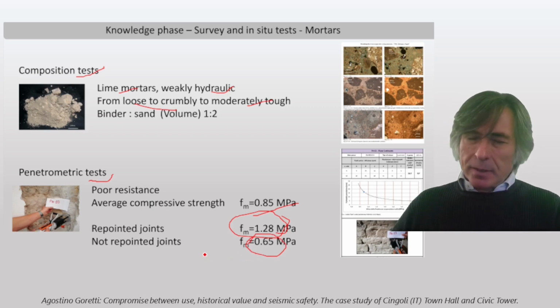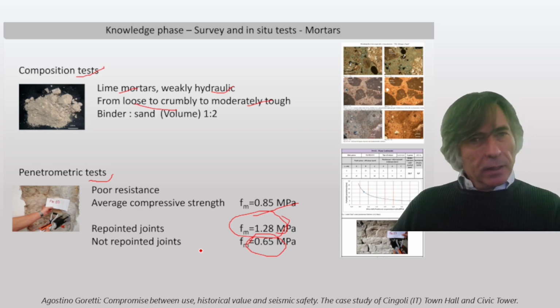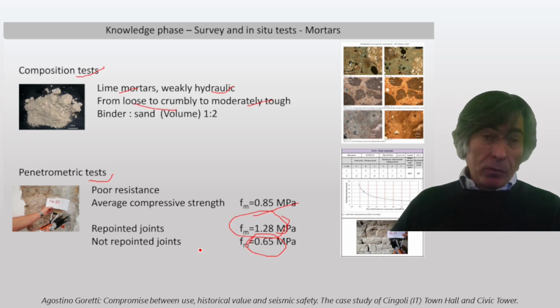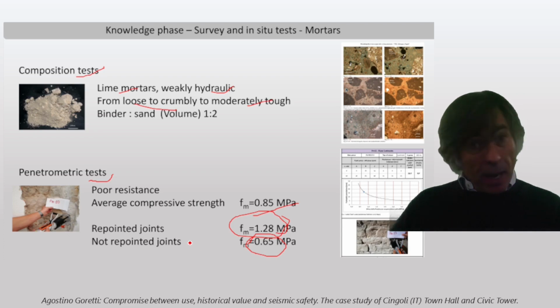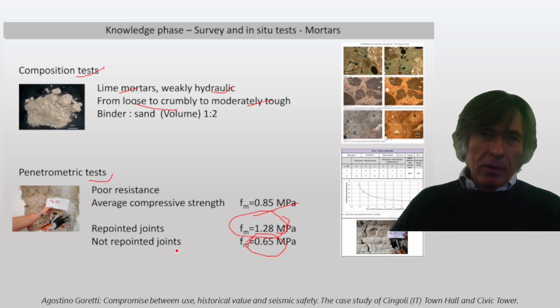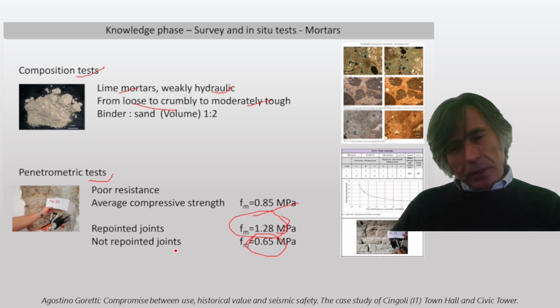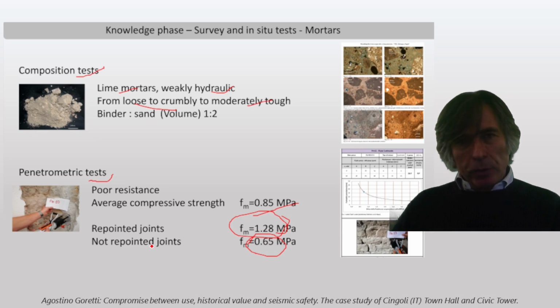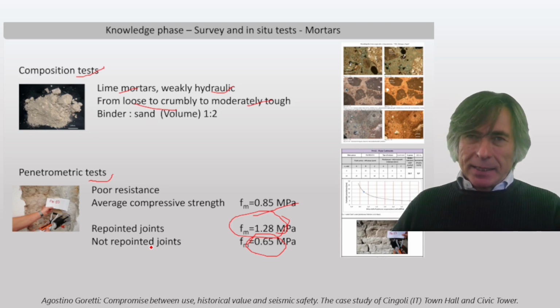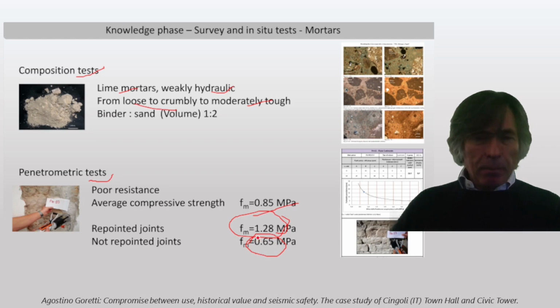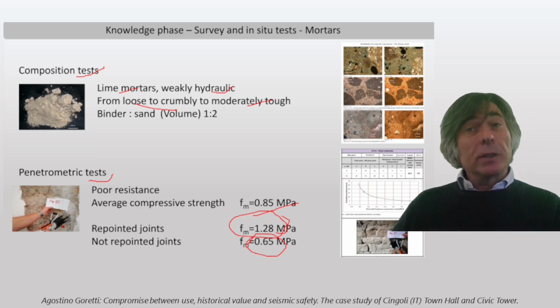Since the repointing of the joints is only in the initial, I would say, 7 centimeters, maximum 10 centimeters from the surface of the wall, then with such large walls, 1.5 meters, 2 meters, we may expect that for the internal part the resistance of the mortar is in the order of 0.6, because it has not been repointed.